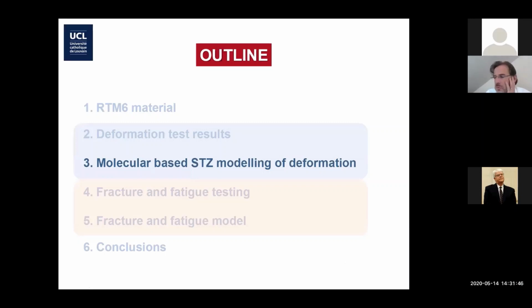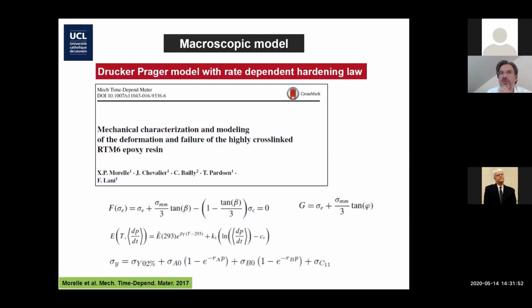Okay, so let's go to modeling now. The first thing we did, with Xavier Morel in his thesis, was to look at available empirical, phenomenological models in order to use this model for composites. So then to make the simulation I mentioned at the beginning, simulate a UD composite with a nice constitutive model for the matrix, then the fibers, turn the crank, and get good predictions. And you know the story, we're not getting very good predictions.